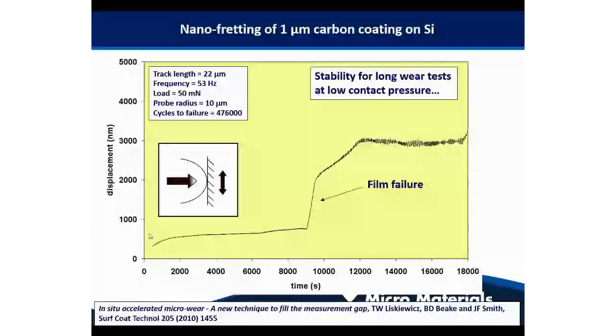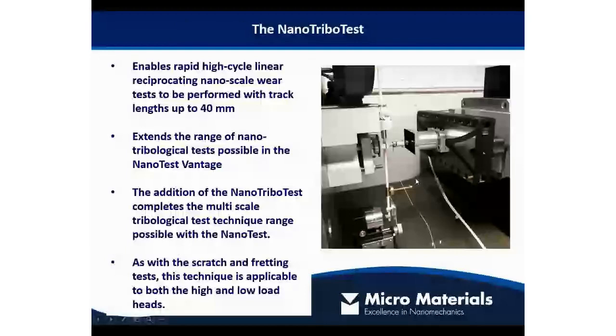In terms of instrumented test data, what we tend to look at is displacement here, which means depth of the probe into the sample as a function of time or as a function of cycle number. What tends to typify or give us an indication that a failure has occurred is a sudden increase in the depth. So here we see an increase of about 1.5 microns. This is a 1 micron coating on a silicon wafer. So there's a very clear failure event taking place here.